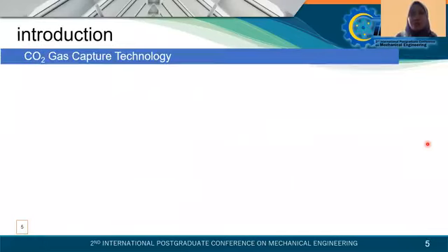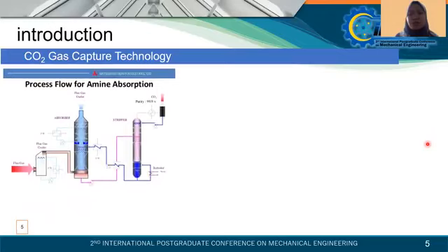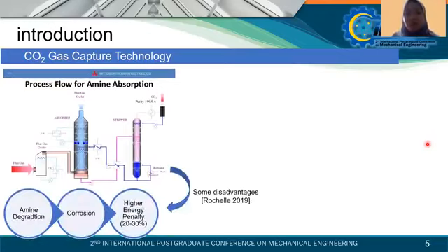need the technology to reduce or to capture the CO2 molecule, because renewable energy is considered to be the long-term plan. Right now, in the industry, in the power plant and also the cement industry, they use the amine absorption to capture the CO2. However, this technology has some disadvantages. They are the amine degradation, corrosion, and also a higher energy penalty of up to 30%.